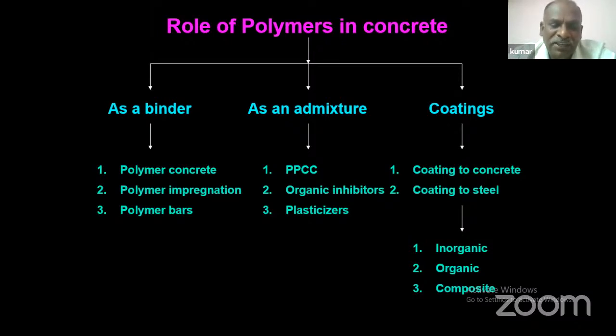Polymer concrete and polymer impregnation were used for repair and rehabilitation. Polymer concrete can be used as an overlay when you are doing repair and rehabilitation. And for polymer impregnation, whenever degradation has happened, you can use polymer impregnation that will arrest the carbonated concrete, and it will have good strength there. Next, you can use polymer in concrete as an admixture, and it will also give very good protection. Second thing, organic inhibitors or inorganic inhibitors. Normally people use inorganic inhibitors, but organic inhibitors can also be used. Then plasticizers, which we normally use in the construction industry.